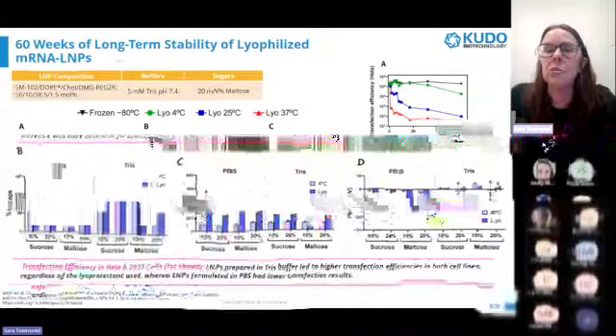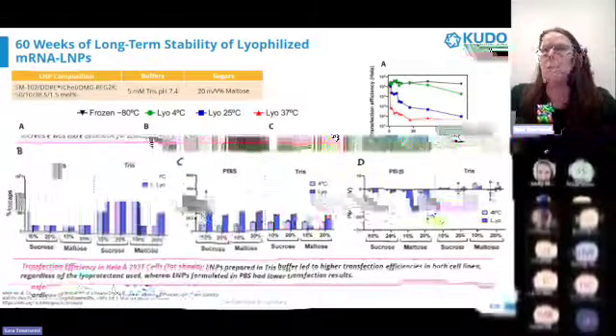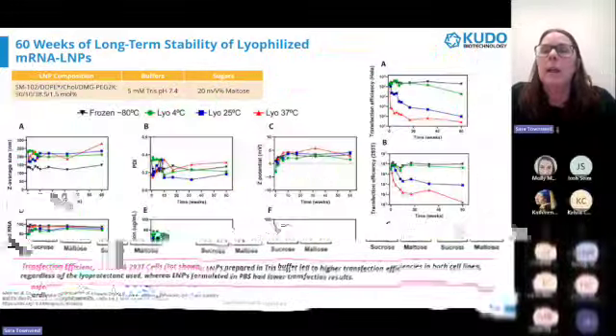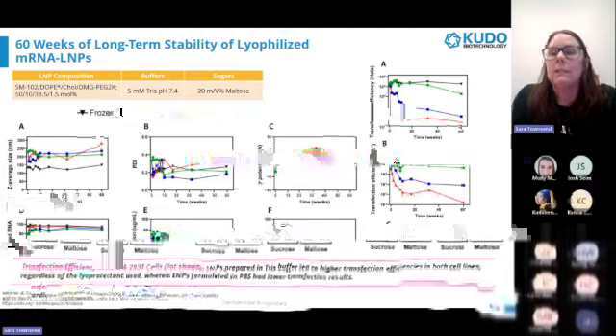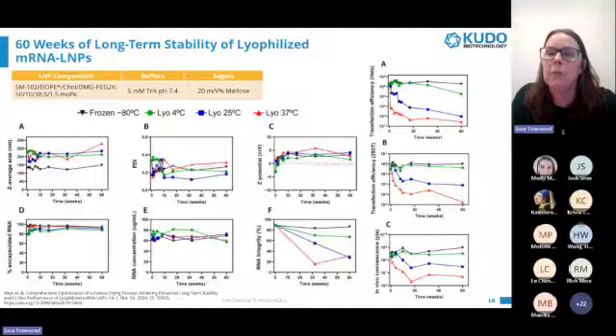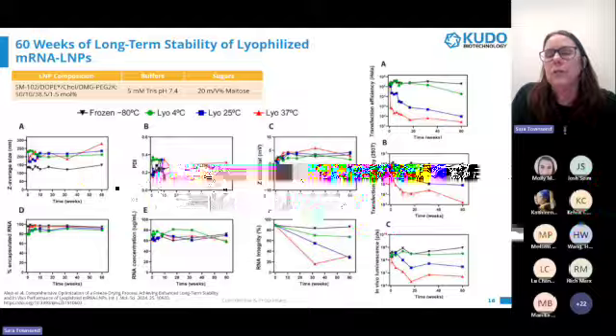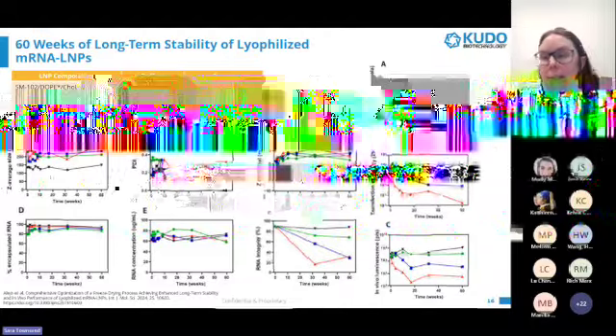After their initial screening optimization of their freeze-drying parameters, they chose 5 millimolar and 20% maltose for their stability. Despite the large particle size at t=0 for their lyophilized LNPs, samples were able to maintain their size, PDI, transfection efficiency, and percent encapsulation for 12 weeks. They dropped below 1%, but still acceptable. The green line here is their lyophilized data.